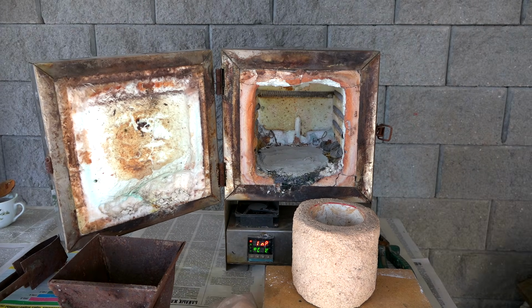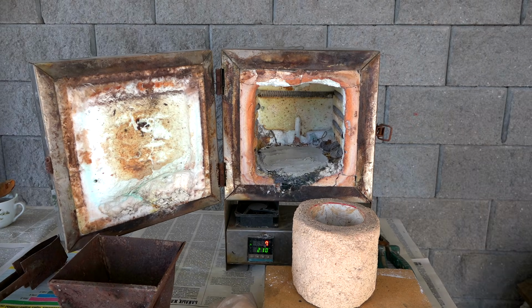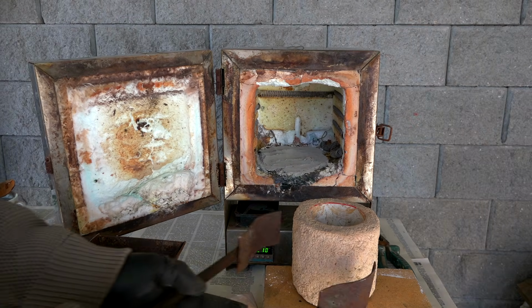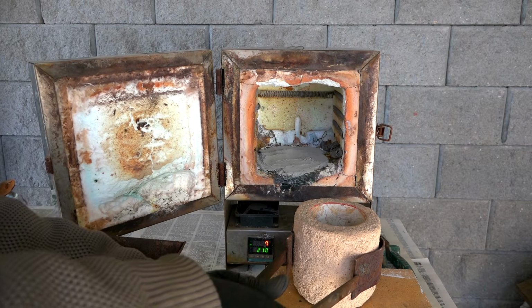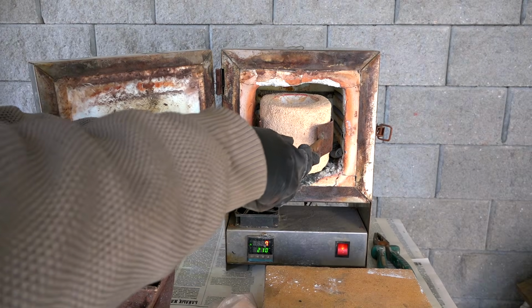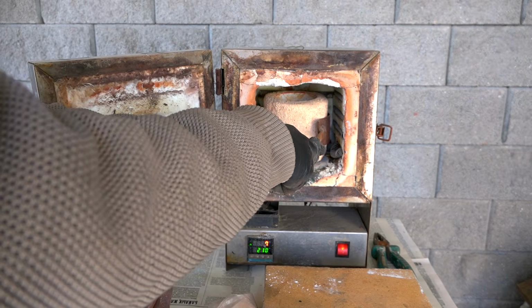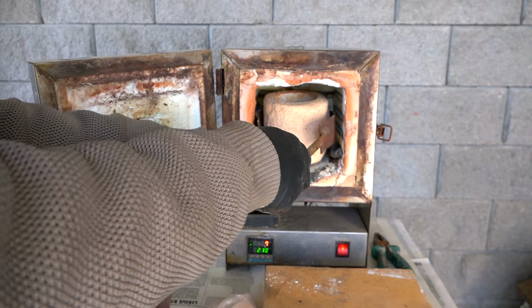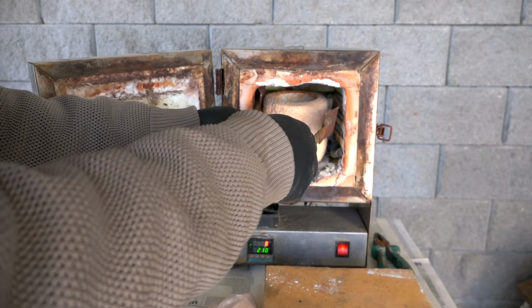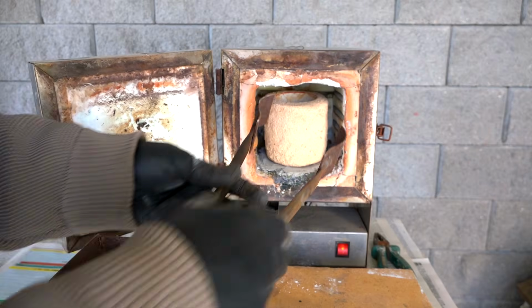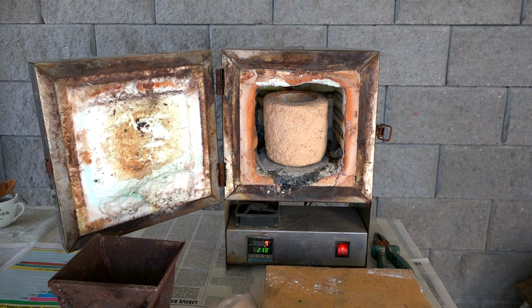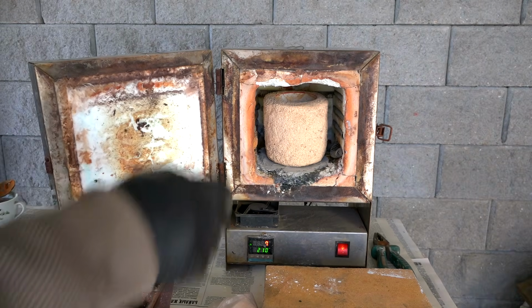Now I turn on the muffle furnace. As you can see, the furnace is already in poor condition and needs to be repaired. The door has almost fallen off. There have been emergencies inside the furnace more than once, when crucibles burst, metal spilled, heating coils burned out, and the thermocouple has long since crumbled. Nevertheless, the muffle furnace is still working, and I am loading the crucible into it. I'll fix it soon. It'll be almost as good as new.